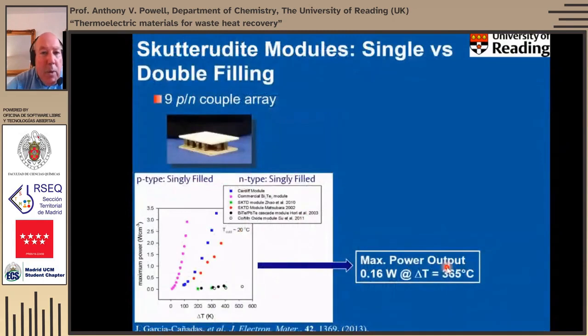So we then started thinking about module construction. We'd previously collaborated with Gao Min at the University of Cardiff on single-filled skutterudites, where the N and P type were both single-filled. So this is one of the modules that they produced from our materials. This is a 9-couple array. And what's referred to in this diagram as the Cardiff module gives about 3.5 watts per square centimeter. If we compare that with the one in pink here, which is a commercial bismuth telluride module, we're getting bismuth telluride performance, but now at somewhat higher temperatures, and we get a maximum power output of about 0.16 watts from this module at 365 degrees C.